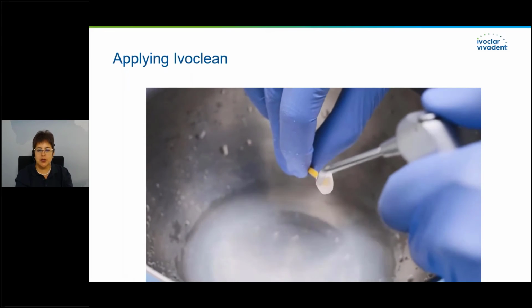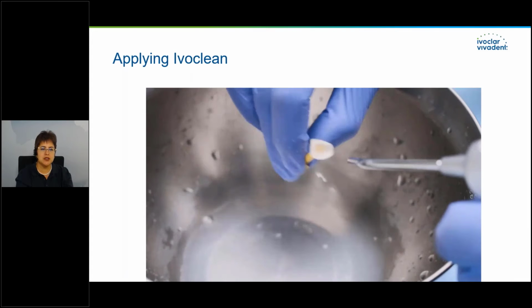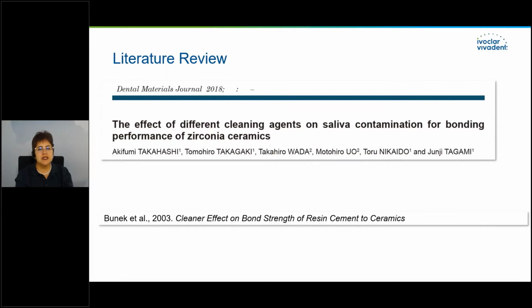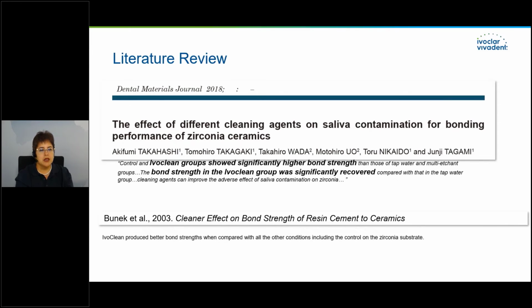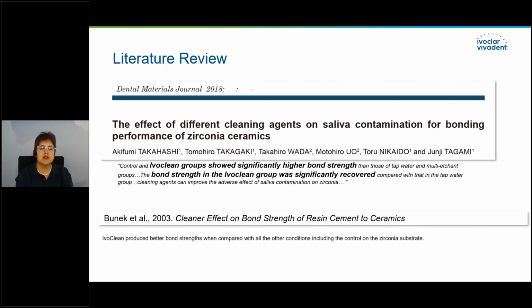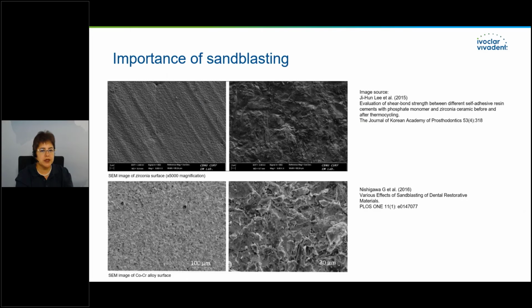So this was a quite simple but important step for zirconia restoration, especially. This is an external study which shows that the Ivoclean group shows similar or better bond strength than the other groups. And I want to show you afterwards also some very interesting SEM. Here you see that hydrofluoric acid on ceramics will increase the surface. The upper pictures are done on zirconia with sandblasting, and here we have sandblasting on metal.